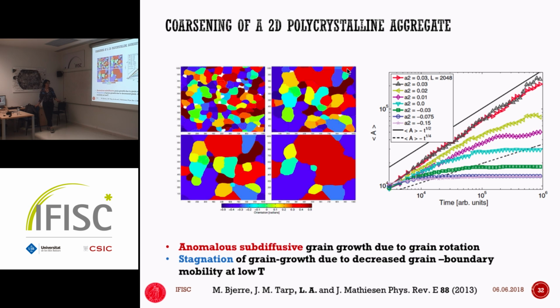One particular mechanism that we have studied is this grain rotation and the grain stagnation. If you quench the system even further, this coarsening is going to stop. So you cannot really go directly to the homogeneous state. The material is going to be metastable for a very, very long time with the grains. You cannot get rid of the grains.